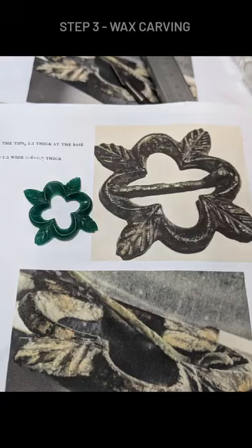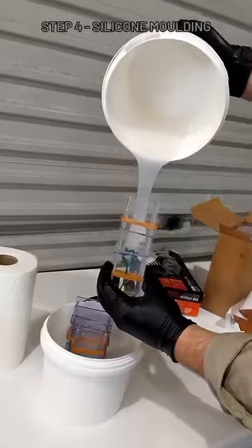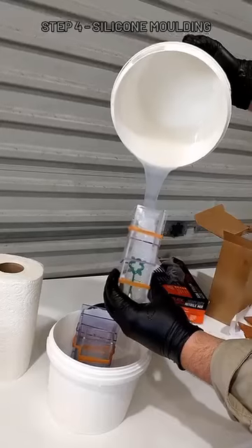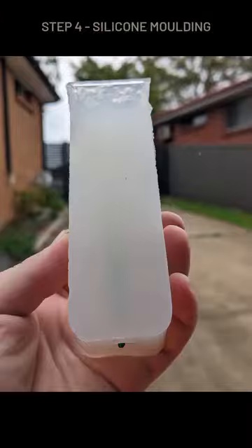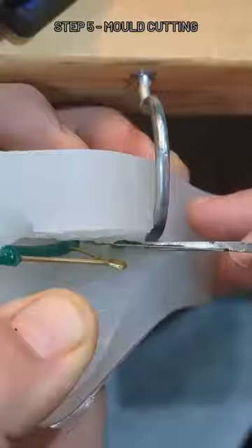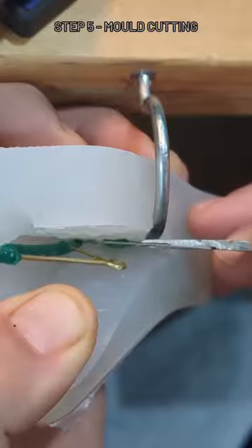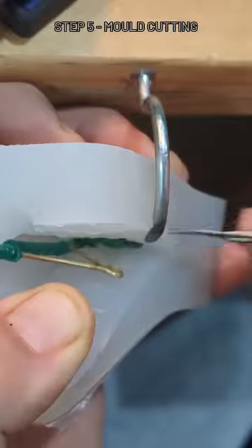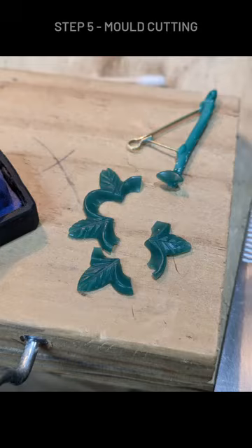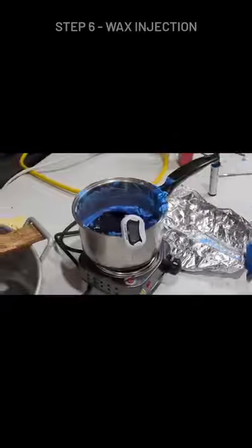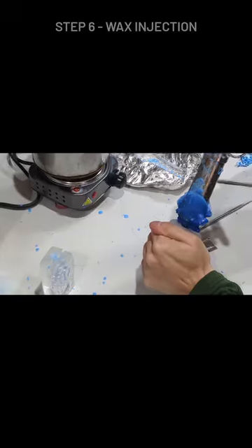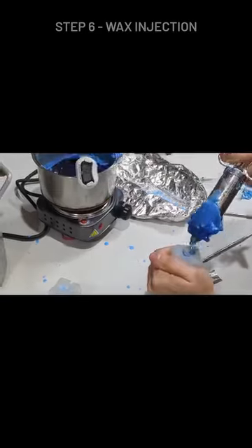But once we're happy with our wax, it gets set inside a 2-part silicone rubber, and 48 hours later, once that rubber has cured, it can be cut open again to reveal a 2-part mould. Sadly, the wax master doesn't always survive this delicate process, but fortunately, we can now recreate infinitely many new copies by injecting molten wax into the silicone mould.